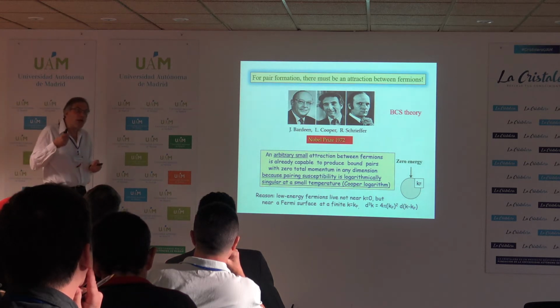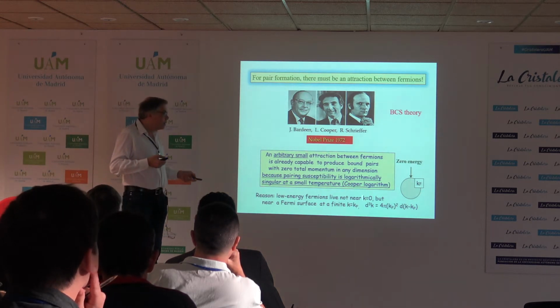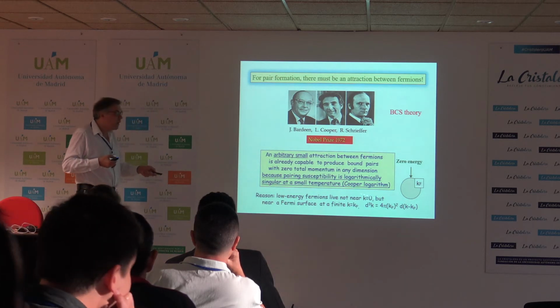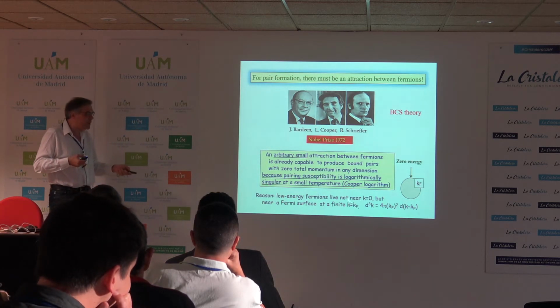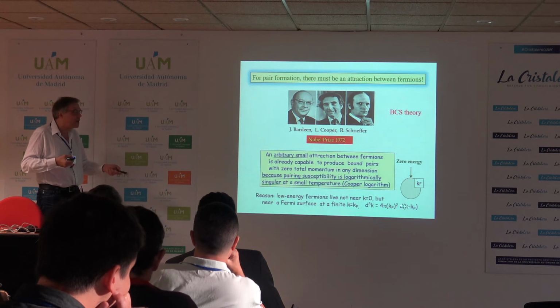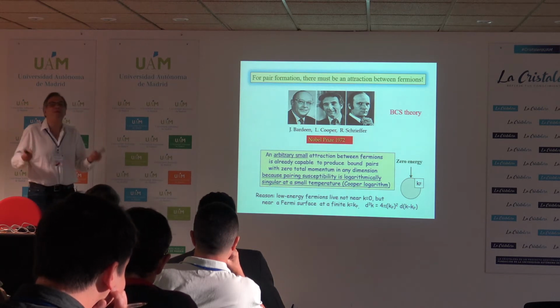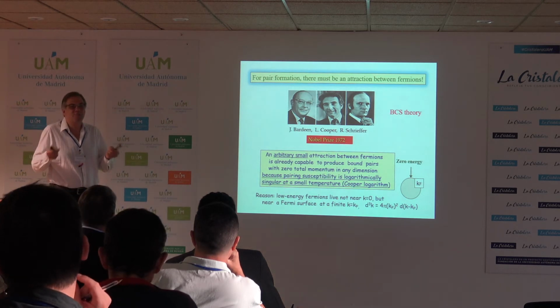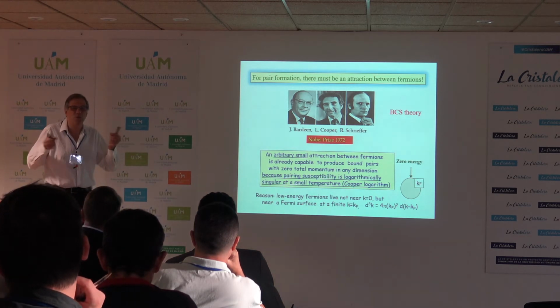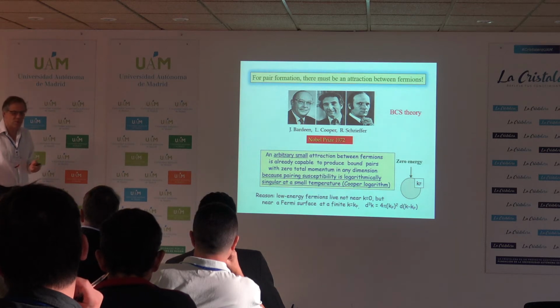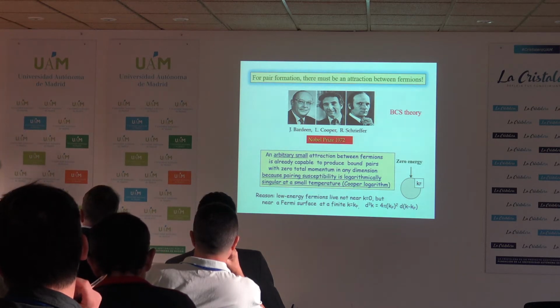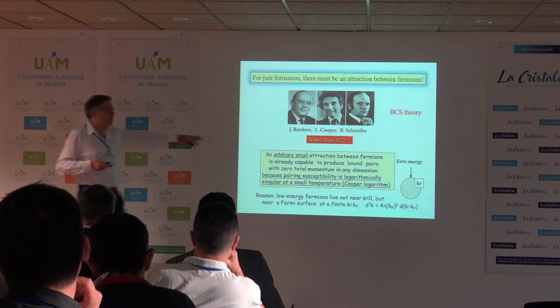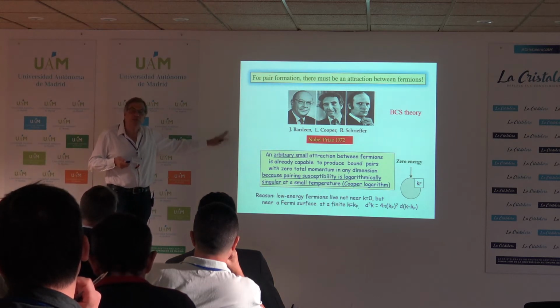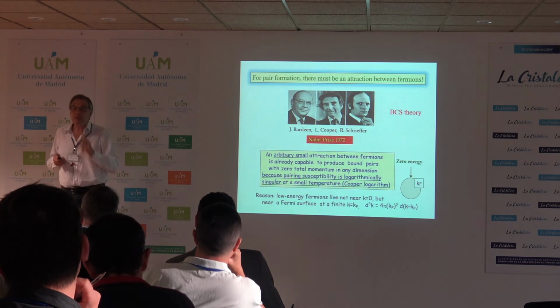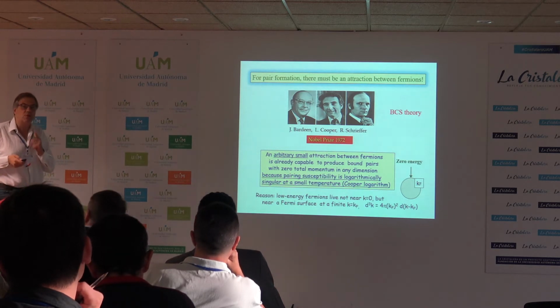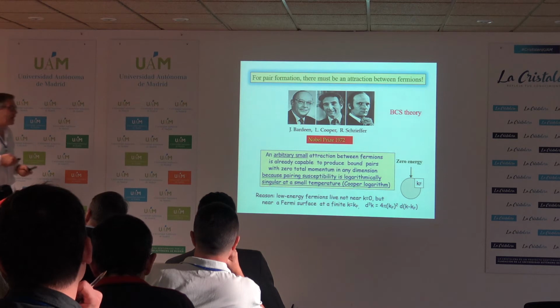And so every time we need to take fluctuations and integrate over 3 components of momentum, or 2 components of momentum, it doesn't matter, the result reduces to a one-dimensional equation. So in fact, the problem reduces quantum mechanics to 1 plus 1 dimension, 1 in space, 1 in time, and in 1 plus 1 dimension, you always get a bound state. So that was one part. Arbitrary weak interaction is sufficient. There is no threshold. Not the case, by the way, for phenomena called quantum critical phenomena, and superconductivity adds a quantum critical component.